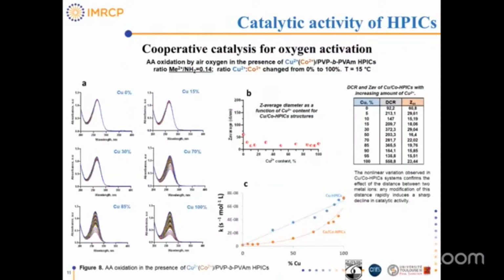Another factor that may influence the catalytic effect is the distance between copper ions within the HPICs and the existence of cooperative interactions between copper ions. To verify this assumption, an experiment was carried out using the most catalytically efficient condition at ratio 0.14. To modulate the average distance between copper ions under these conditions, some of them were partially replaced with cobalt ions within the HPICs structure.